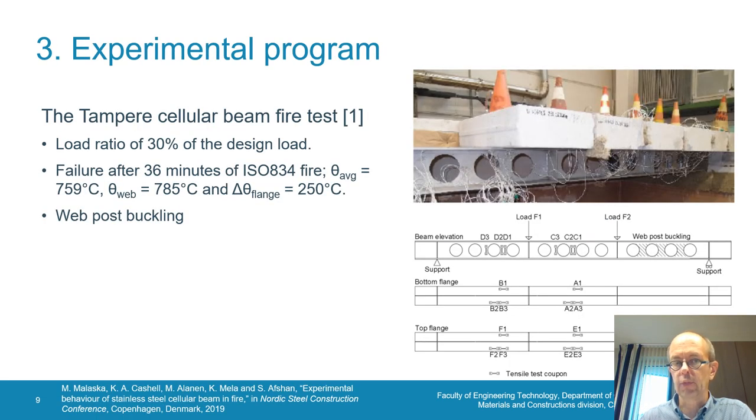Let's discuss the experimental program. At Tampere University, a cellular beam was loaded until 30% of the design load and submitted to an ISO fire. After 36 minutes, failure was observed due to post-buckling at the right-hand side of the figure, and the test was stopped. From this beam, some test coupons are taken, like shown on the figure, and tested at Tampere University.